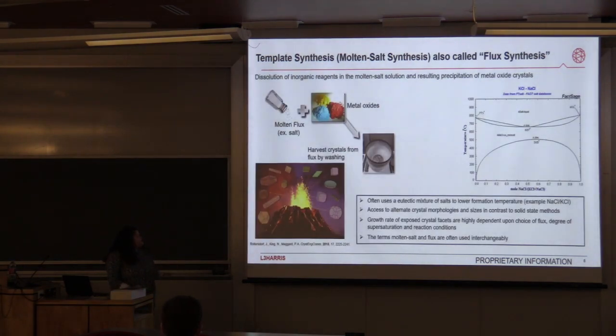And the way we do that is we use a molten salt process. Really, it's just adding salt, sodium chloride, potassium chloride. We like to use eutectics because then you can actually lower your reaction temperature by combining them. Our metal oxides, the reagents, will precipitate out as metal oxide crystals. It's used in a lot of different things, to target alternate crystal morphologies that we wouldn't be able to otherwise get.